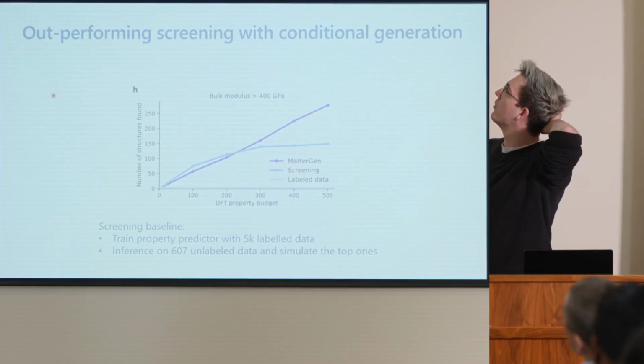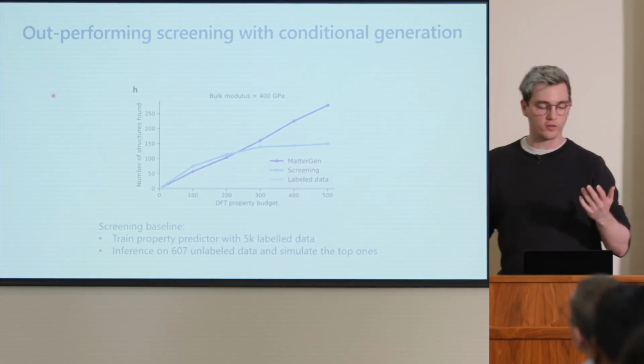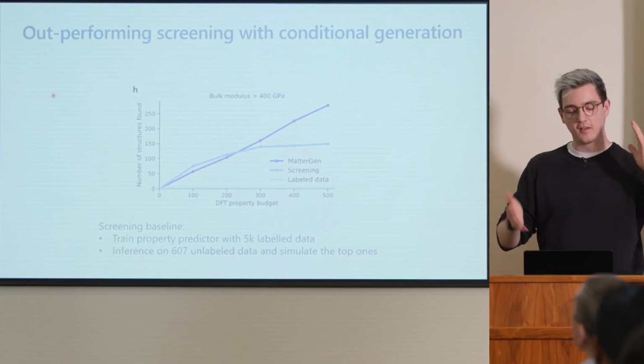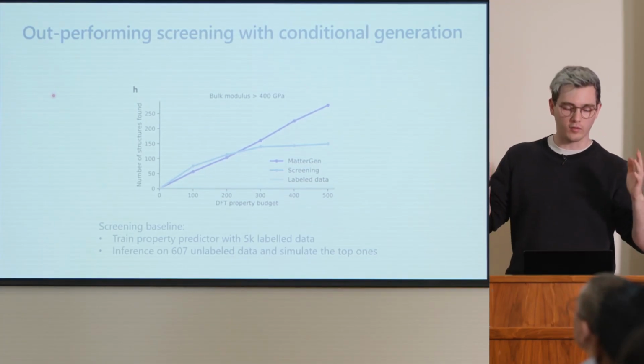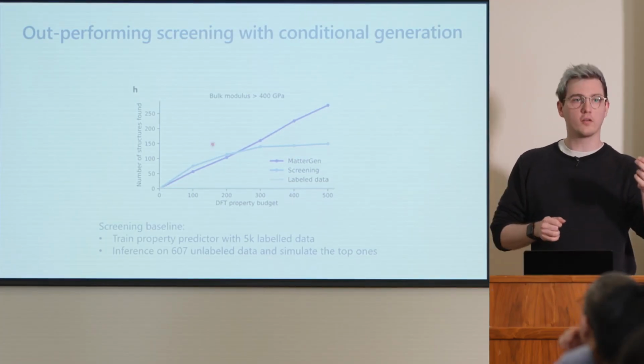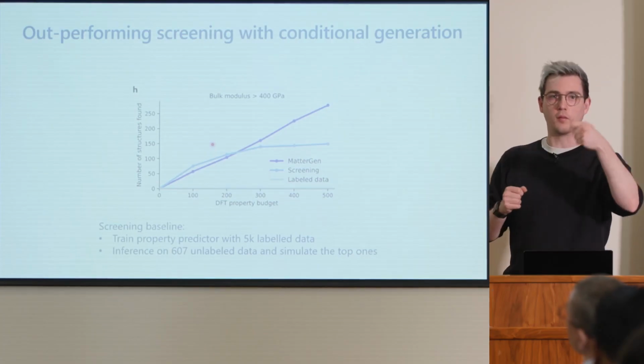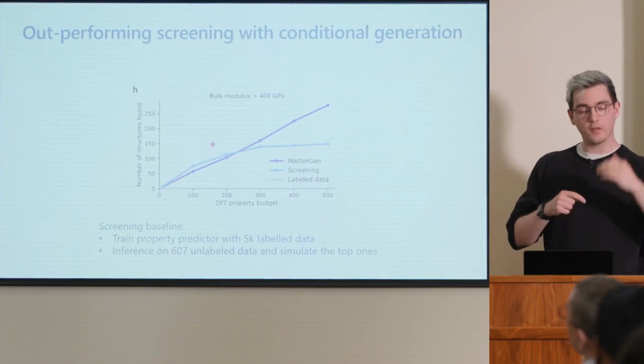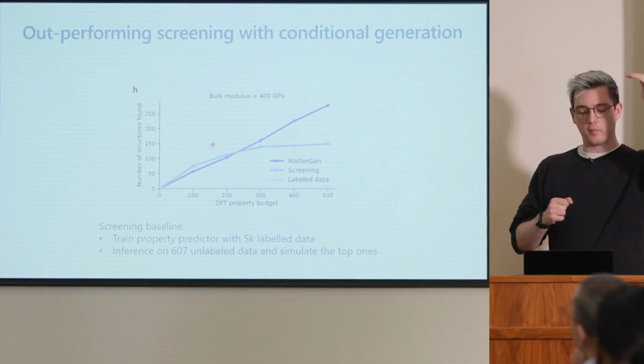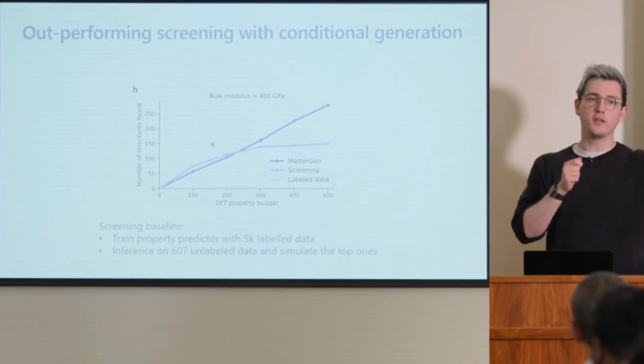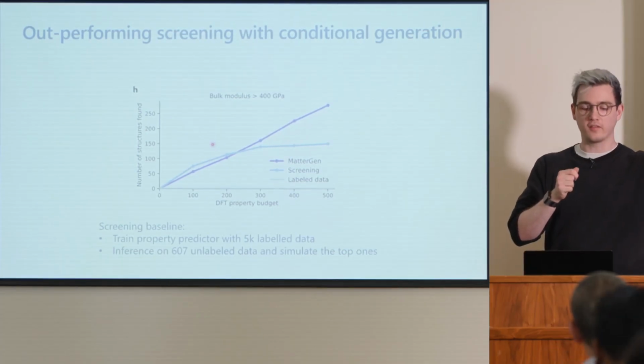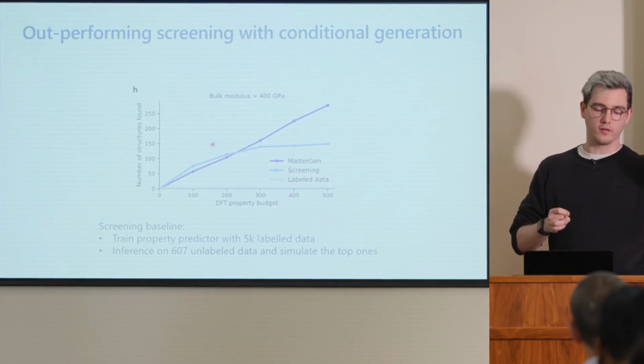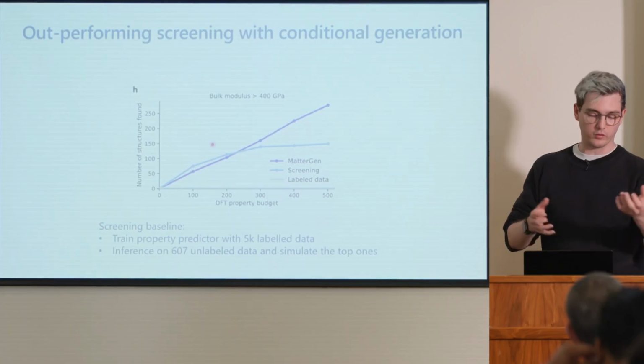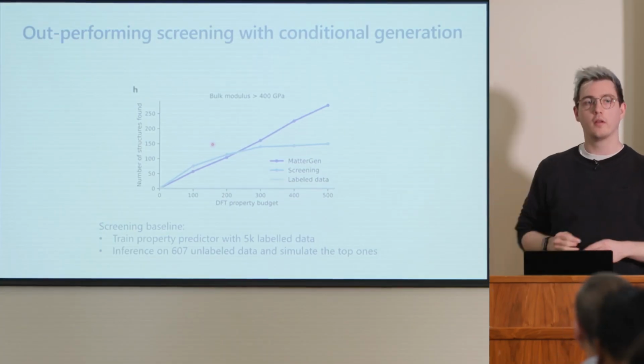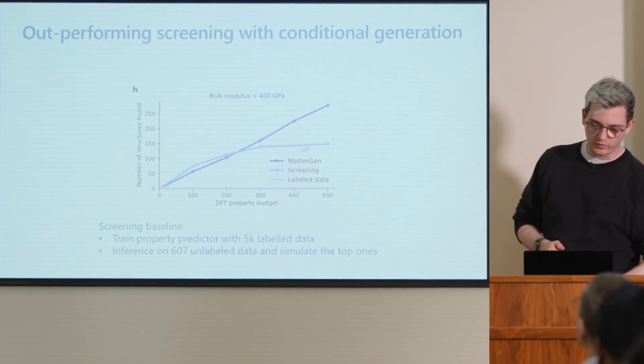We also compared to a more traditional approach where you have a set of materials, which in our case is these 600,000 or 1 million reference data points, and you use a property predictor that predicts the bulk modulus, the hardness of a material, and then you just go through your list in descending order. So you start with the one that is predicted to have the highest bulk modulus, you pass it to DFT, the best computational method you have to estimate it, and if that satisfies the constraint, then you're happy and you keep it, and then you just keep going down. And this is what we see with this screening curve here.